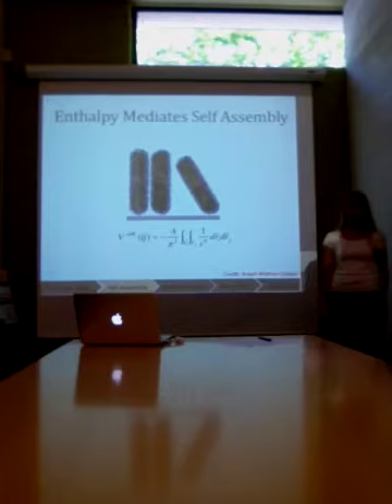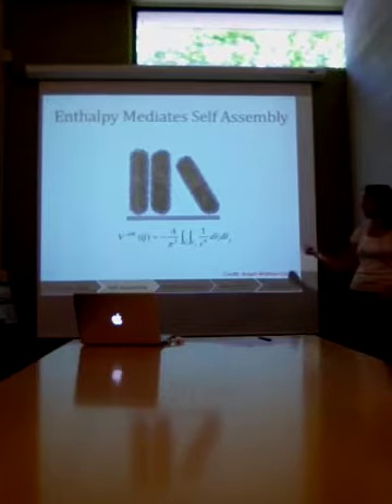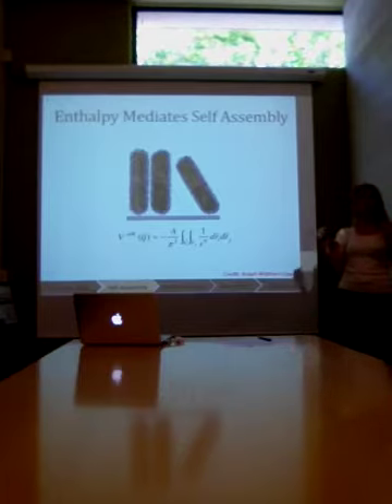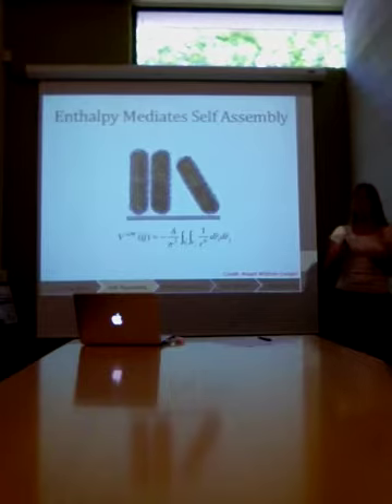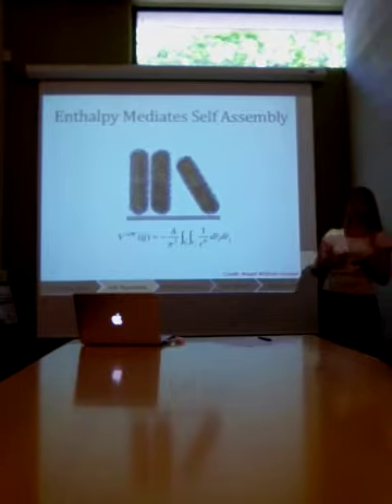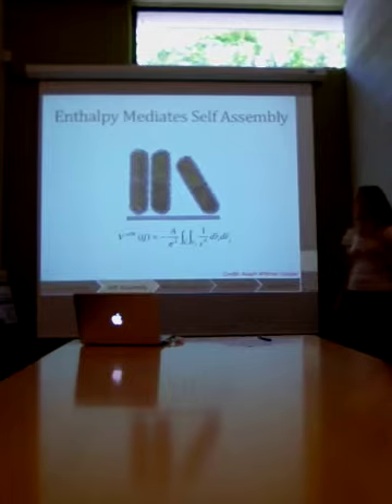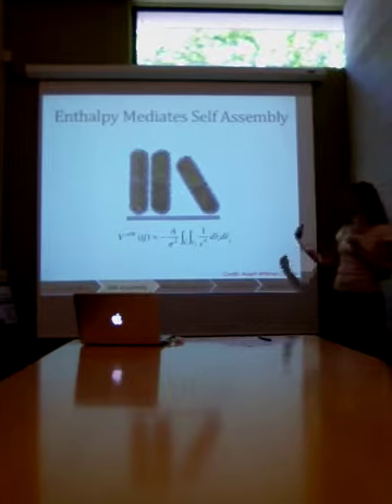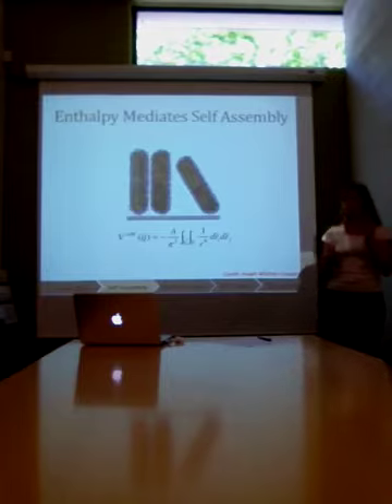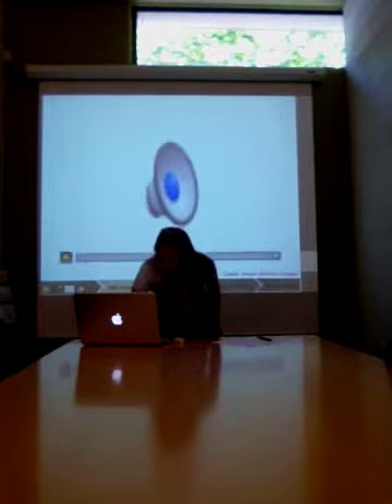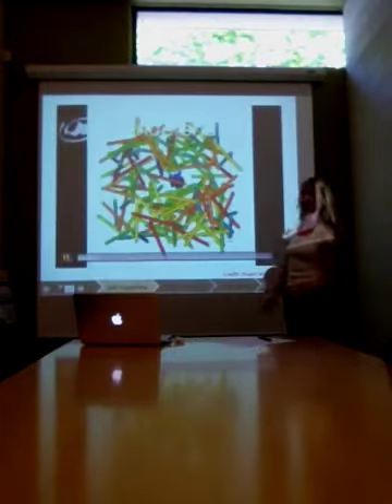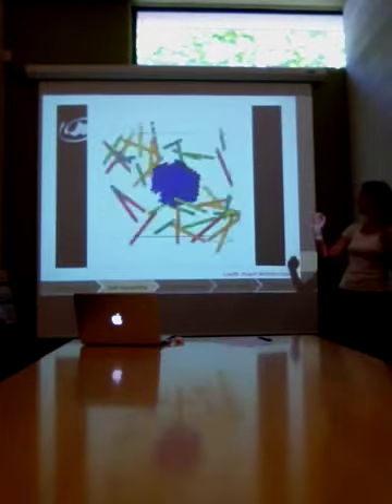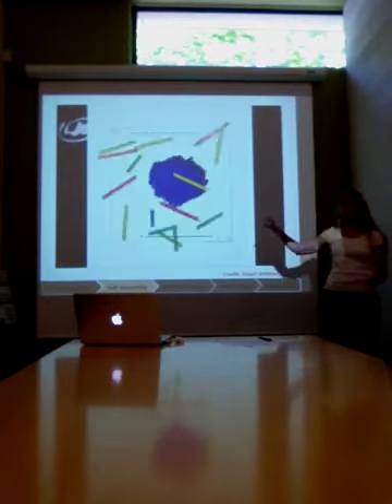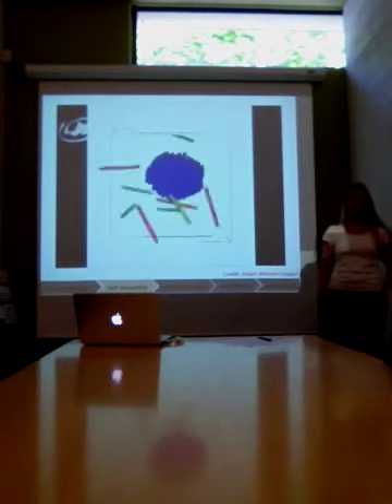Because we're working in a nonpolar system, we look at the van der Waals interactions between all the components of our system. So the substrate, the solvent, the nanocrystals, and the ligands that are attached to them. And Asaph Widmer-Cooper and Phil Geisler did molecular dynamics calculations to calculate the exact forces between each of these components. And they plugged them into a Monte Carlo simulation in which they could watch the nanorods start to pack together. And what they saw was very similar to what we were seeing experimentally.